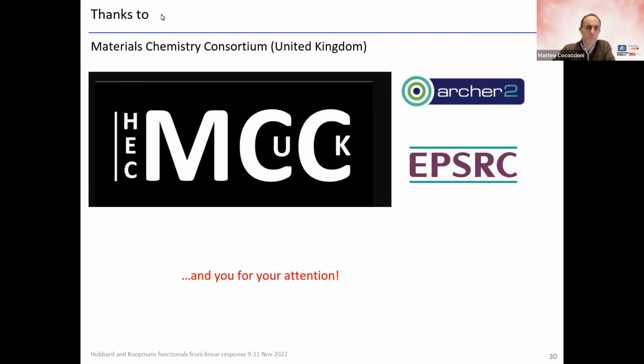So sorry, could you repeat the last part? The PAW projectors are those living only inside the core radii of each atom, so they don't extend beyond that. So that makes quite a difference with using atomic wave functions instead.